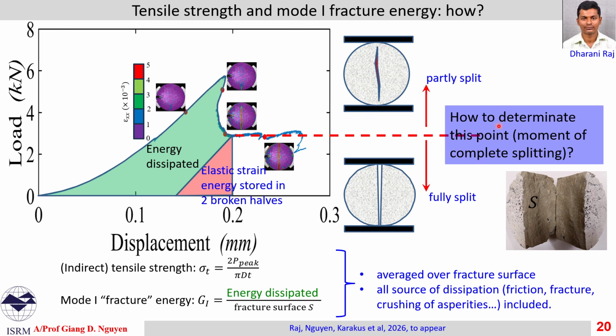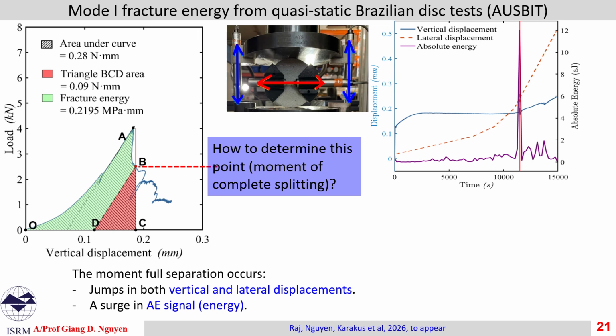So the remaining point is how to determine the moment of complete splitting. We use a few things here to pinpoint when it is fully fractured. First, at the moment of full fracture, we observe in all tests so far a jump in both vertical and lateral displacement. If we plot them together, at the moment of complete fracture, the lateral one exhibits this kind of jump, the orange one.